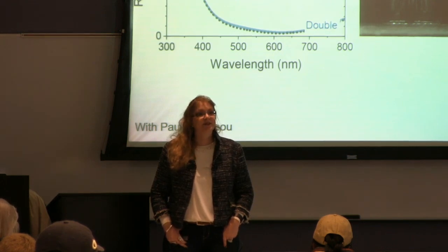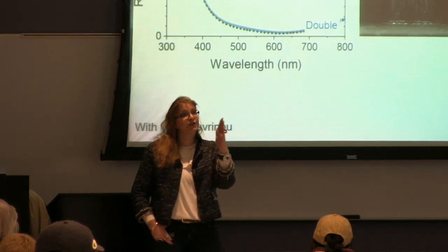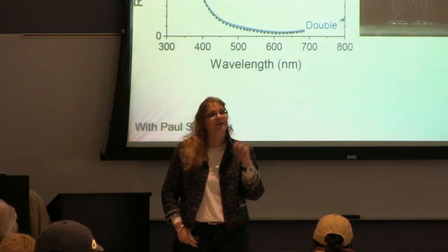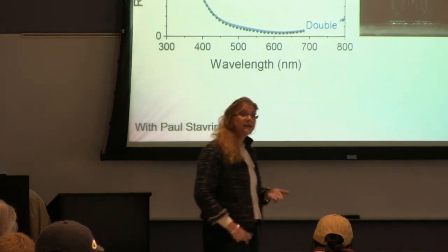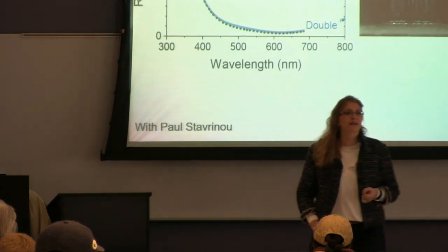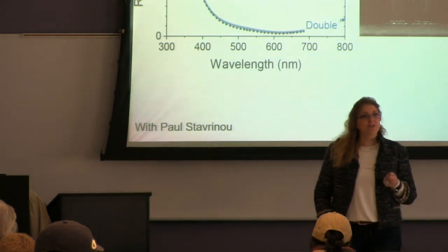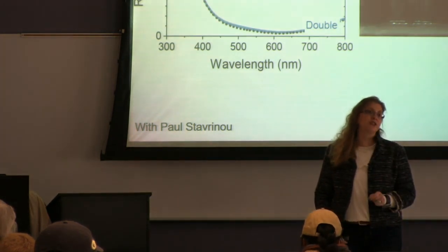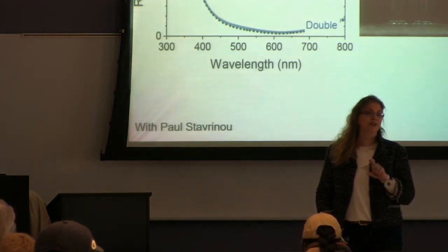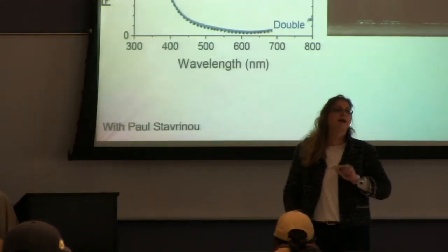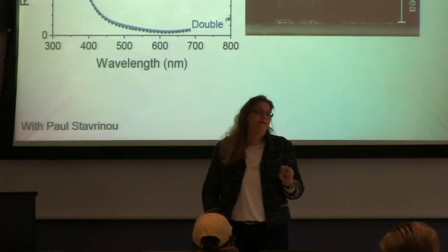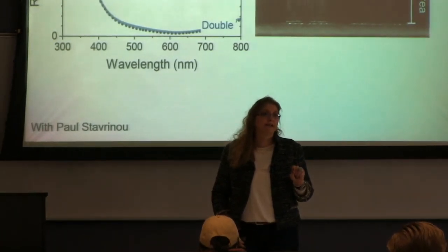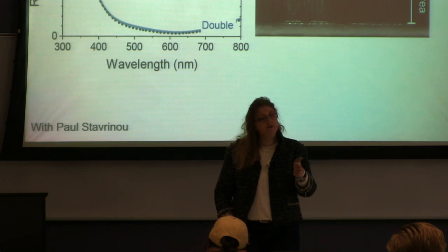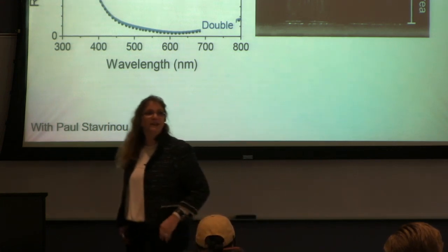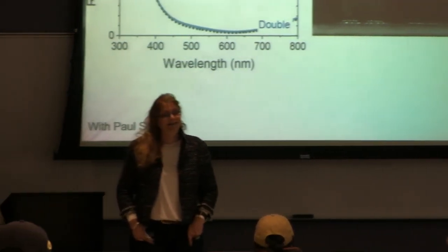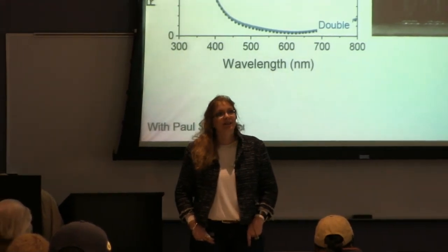Yes, it does, as I mentioned. So you see that, that's why the mirror shifts to lower wavelength. When we make mirrors, we anneal, and the stop band changes. In case it would not change the thickness, the intensity of the reflection would only get enhanced because you change the refractive index contrast, but it also shrinks. But in a very reproducible manner, we know exactly how much it shrinks, and therefore we can shift the stop band. So you can actually make a bit of a temperature sensor with it.